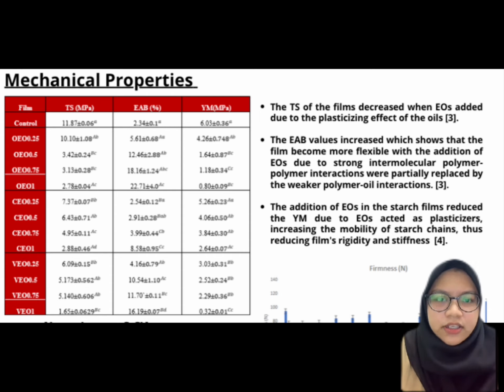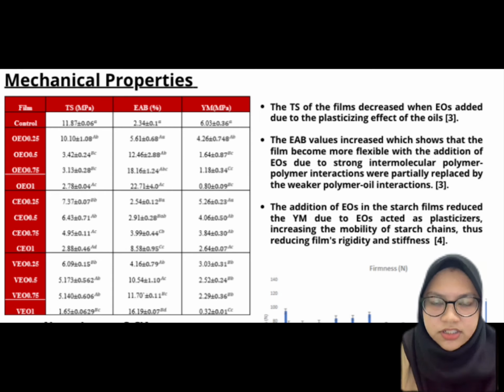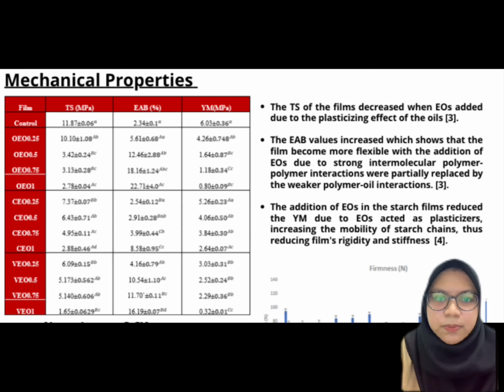Next part is the film mechanical properties. The table here shows that there was a decrement of the tensile strength when the essential oil is added, due to the plasticizing effect of the oil. The EAB value, the elongation at break value of the film, increased, showing that the film became more flexible with the addition of the essential oils, because the strong intermolecular polymer-polymer interaction was partially replaced by the weaker polymer-oil interaction. And finally, the addition of the essential oil into the starch film reduced the Young modulus value of the films because the essential oil acted as a plasticizer, increasing the mobility of the starch chains, thus reducing film rigidity and stiffness.